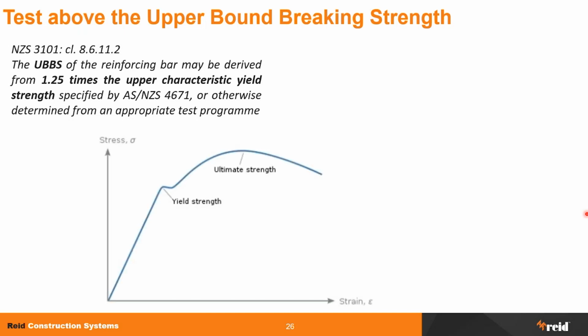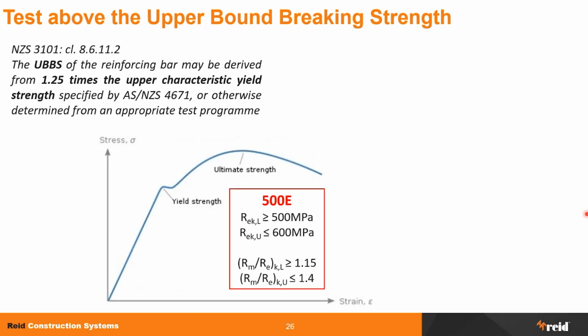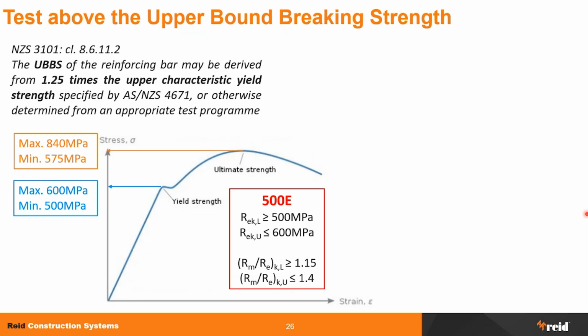So when we look at the reinforcement bar, the behavior that is required by AS/NZS 4671 for a 500E grade is that the lower characteristic yield strength needs to be above 500 megapascal, and the upper characteristic yield strength below 600 megapascal. And also that the ratio between the ultimate capacity and the yield needs to be between 1.15 and 1.4. Therefore, if we multiply with the yield, we get that the ultimate in theory could be between 575 and 840. This is the full range.